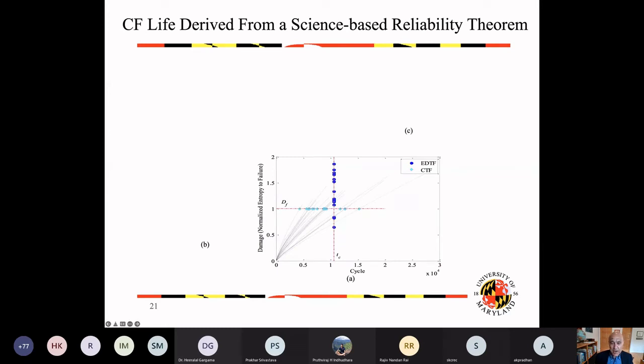So if you look at now my data here, when I look at the 16 data from my experiments, these are the time at which I reach this T of C. And if I put a distribution over that T of C, this is the distribution of my amount of entropy which is generated, okay? This is, of course, normalized entropy, and it shows the normalized amount of entropic distribution. And if I now take this distribution and convert it based on the previous equation which I showed you to the time of failure distribution, then I get this red distribution which is derived from my entropy calculation.